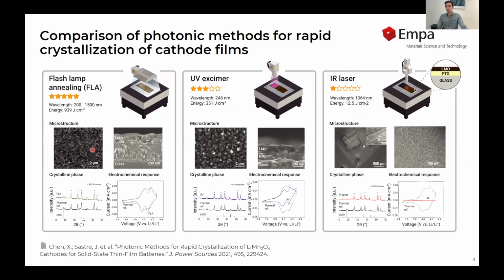For example, here we have the microstructure. We see crystalline LMO after the crystallization step, the photonic crystallization step. We also observe a perfect crystalline phase, equivalent to the thermally annealed one, and also corresponding to the reference pattern. And from the cyclic voltammetry measurement, we also observe the two lithiation steps of the spinel LMO, which is what we expect from such a cathode film.